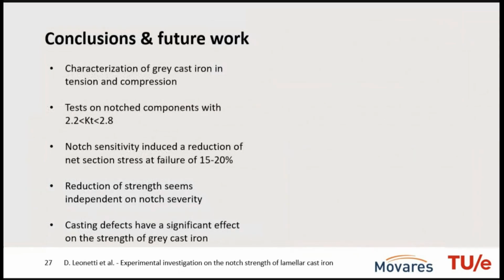So going to the conclusion, we propose this characterization of gray cast iron in tension and compression, performing tests of notched components with a theoretical stress concentration factor between 2 and 3, more or less. We observed that the material has some degree of notch sensitivity, and this induced a reduction of net section stress to failure of about 15–20%. And this does not seem to depend on the notch severity, at least for the range of notches that we looked at. But we recognize that casting defects have a significant effect on the strength of gray cast iron.